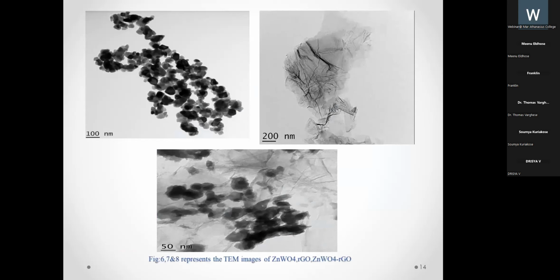And these are the TEM images. This is for zinc tungstate alone, this is for RGO alone, and this is for the composite. It has been seen that the zinc tungstate nanoparticles have been spread on the surface of the reduced graphene oxide.